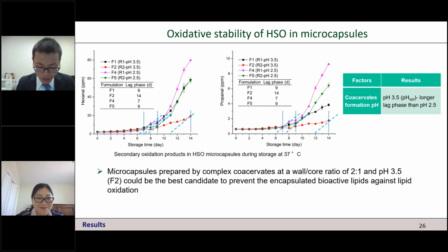Thank you, Dr. Yang. That's a very good question. I thought about your question previously a little bit. It's about salt. I think the mineral, especially the sodium and calcium. I could tell you the major component of the minerals in the PPI could be sodium, and the other components we measured are in very limited amounts. Sodium is typically almost half of the minerals, around 2.5%.